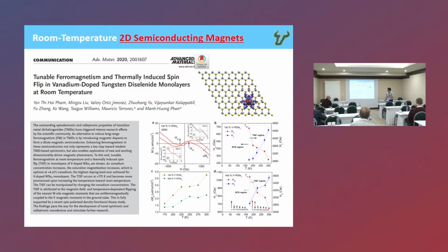So actually, we have weak anti-ferromagnetic coupling, and therefore it matters when you increase the temperature. At high temperature, in this case around 175 K, this temperature makes the coupling become weaker. And when you apply a magnetic field, it is sufficient to flip the spin. And that's why we observe this crossover here in the magnetic hysteresis loop.